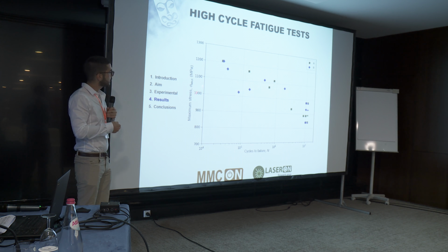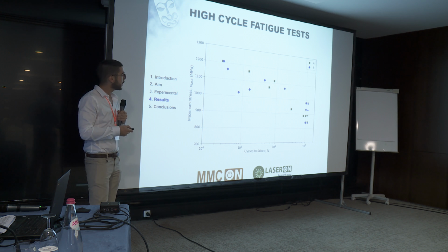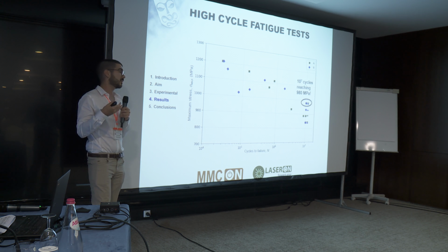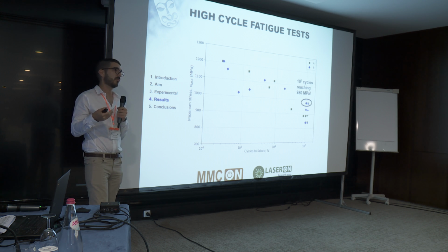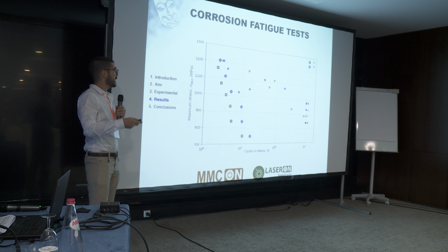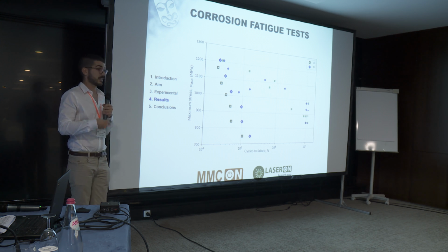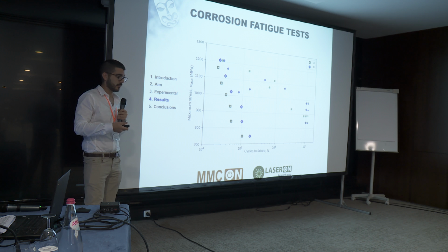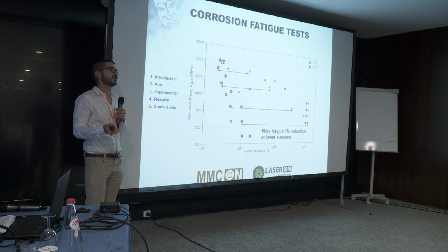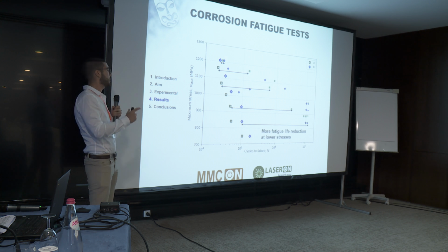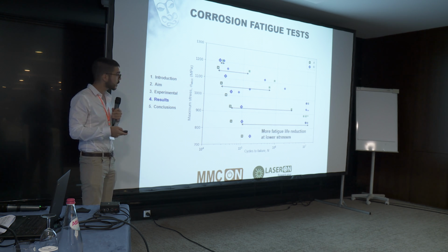On the y-axis we have the maximum stress, and on the x-axis the cycles to failure, and we can see that these steels are able to reach almost 1,000 megapascals during 10 million cycles, which is quite impressive. On the other hand, corrosion fatigue tests led to much lower fatigue lives, and this reduction was more accentuated at lower stresses than at higher ones.